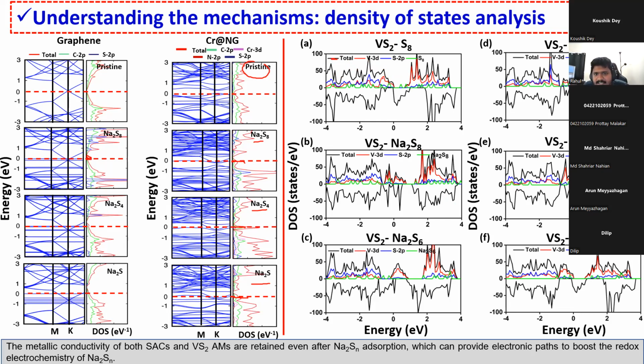And you can see from this density of states that you can ask which state is majorly responsible for this conductivity. We could tell that it is the vanadium 3d state, the red color. If you see at the Fermi level, you can see that the vanadium 3d states are more when compared to other states. And you can see from here that there is some overlapping between the vanadium 3d state as well as the sodium polysulfide. That's basically the bond formation.